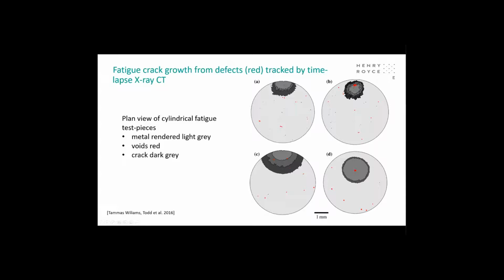But what we can also see, because we can do a time-lapse study, is how those defects change over time, and you can see quite clearly with the grey contours how defects have nucleated cracks, and those cracks have grown over time. So in the top left and the bottom left, you can see defects that have formed near the surface, and we can see how the crack has propagated from the surface, whereas in the ones on the right, we can see somewhat larger defects, but those larger defects, of course, cracks grow in the interior.